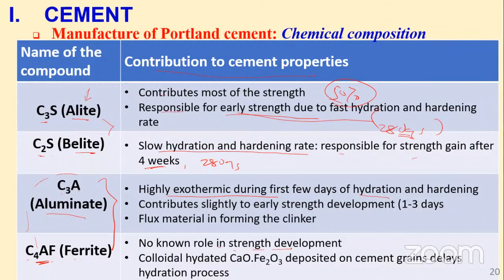So you want to have ample time. You don't want a cement that hardens immediately you mix it with water. But if this reaction is allowed to proceed without control, because of the very high heat that is generated, it's going to result in very quick hardening of our cement, which we call flash setting. Our cement paste or our concrete will stiffen very fast. And this is not a desirable characteristic because we will not have adequate time to place, vibrate and compact our concrete. Therefore, we need to control this reaction by bringing in gypsum. So that's why gypsum is added during manufacture of cement.